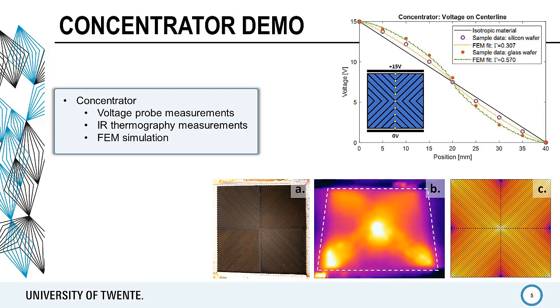Voltage probe measurements and infrared thermography measurements showed the concentration of current through the center with a higher voltage gradient. These kind of structures are interesting for sensing by, for example, increasing the sensitivity locally in 3D printed sensors.